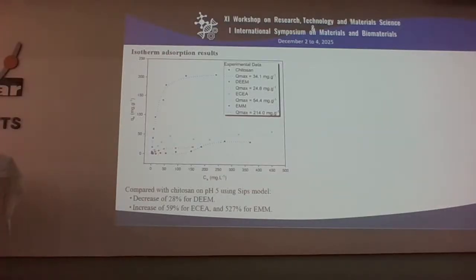So the isotherms showed something incredible for us. For pH 5, using the SIPS model, we can see the chitosan here in black with a maximum adsorption of 34 milligrams per gram of chitosan. But if you look at the modified ones, they have a really high increase. It's about 59% for ECEA and 527% for EMM, the maximum adsorption.